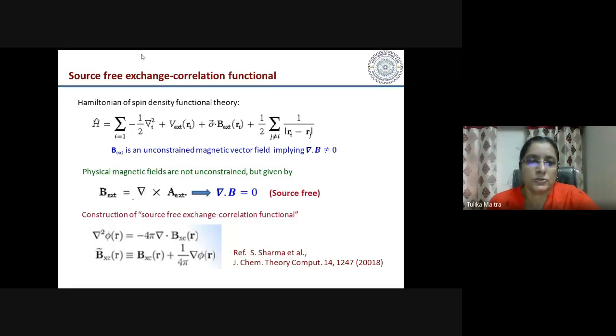So what is done in the source-free exchange correlation functional is that this magnetic field is made source-free. That means it can be written as a curl of a vector potential. Okay. So to make it source-free, one can solve this Poisson equation and find this phi, and adding this del phi to the existing magnetic field, one can construct a new exchange correlation magnetic field, which then becomes source free. Okay, so by using this method, the exchange correlation functional was made source free, and we used it for our systems.